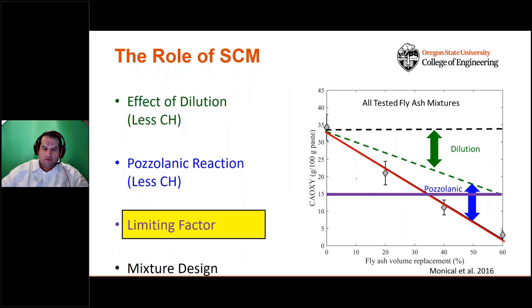So how do we solve this problem, or what are some of the potential solutions? Well, one of the simplest solutions is to dilute the system, to use less cement. So the first thing you can do is use less cement in general. Lots of times people say, well, I want to use more cement because I want to make it stronger. By using more cement, you make more calcium hydroxide. By making more calcium hydroxide, you make more calcium oxychloride, right? You've actually exacerbated the problem, not solved the problem.